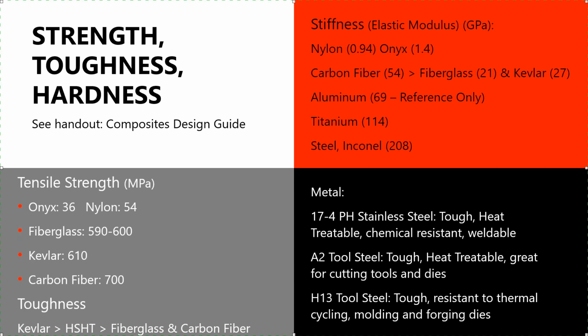When it comes to strength, however, that's where you see ONYX and nylon. Nylon theoretically has a higher strength, but because ONYX is stiffer, it seems stronger, right? And the nylon fibers might start to fail a little bit sooner because of that stiffness. So you get a little bit more toughness with the nylon. Toughness with Kevlar is also a big thing. So you get your toughness when you stay away from the carbon fiber. But fiberglass, Kevlar, and carbon fiber are all going to give you a lot of really fantastic strength.